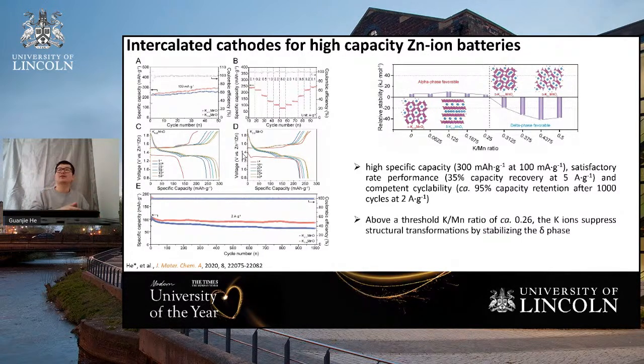We did a lot of collaboration with theoretical collaborators, and we discovered there's a threshold for the potassium to manganese atomic ratio that is around 0.26. So the potassium ions can suppress the structural transformation by stabilizing the initial structures of the manganese oxide. That's why it can realize a very stable performance.